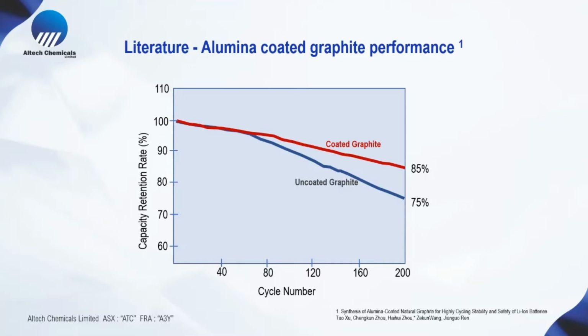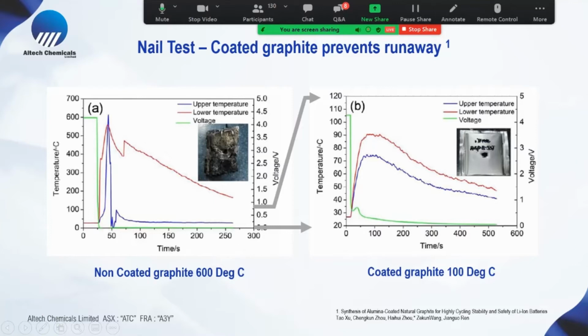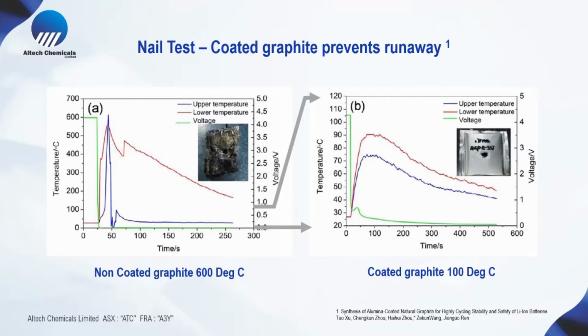This is an example of some of the research that shows coated graphite versus uncoated graphite. And after 200 cycles, you can see that the coated graphite has 10% more energy capacity than the uncoated graphite. Now, I mentioned the safety side. This is an example of research that shows on the left-hand side a non-coated graphite battery, and they do a nail penetration test. And you can see the battery catches fire, with a temperature of 600 degrees. But on the right-hand side is coated graphite, and the temperature only gets up to 100 degrees, and you can see the picture of the battery remains intact.